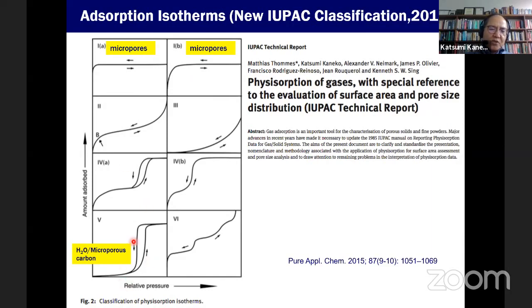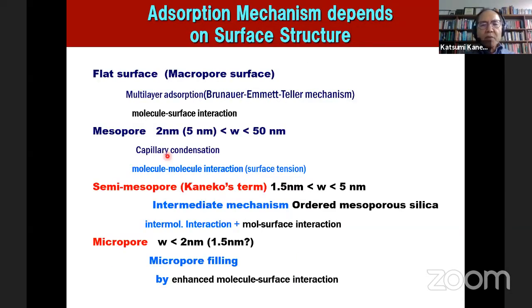And this is a special case: water adsorption on microporous carbon without oxidation often shows this adsorption isotherm. But this does not come from capillary condensation. The adsorption mechanism depends on the surface structure. For a flat surface, and also a very large macropore surface, the BET theory can be applicable. Representative mesopores, in my case, I want to say more than 5 nanometers. Then for 5 nanometers to 50 nanometers, capillary condensation theory can describe the adsorption behavior.